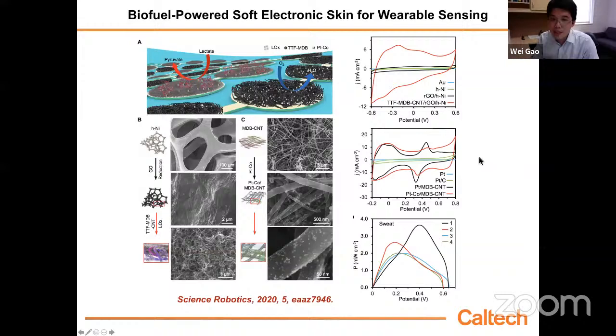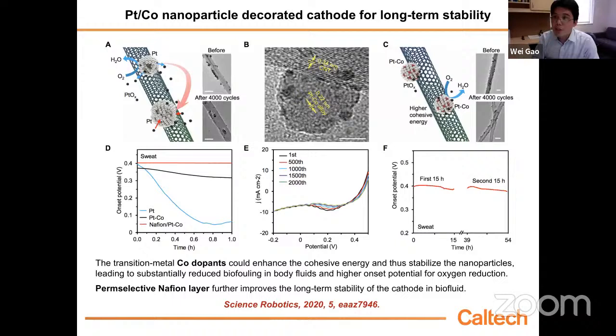For this platinum cobalt nanoparticle decorated carbon tube, they show very good stability. Because typically, people use platinum as a catalyst, and platinum can be easily poisoned by body fluid, that's why they're not very stable. If you use silver chloride as the cathode, they are consumable. That's why they cannot last long either. So by using these platinum cobalt nanoparticles, this biofuel cell can work for a prolonged period. The reason is that this cobalt dopant can enhance the cohesive energy and enhance the stability of the particle.